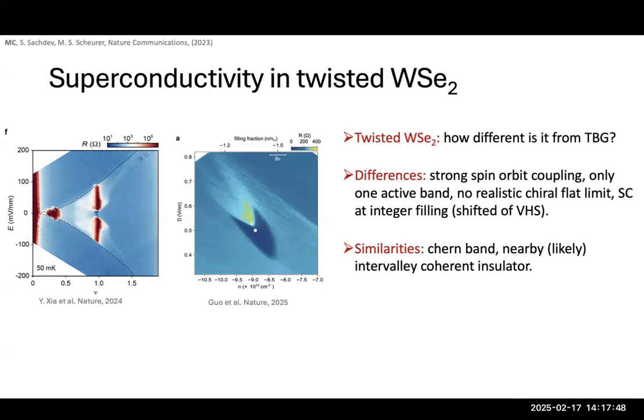And then in the Columbia experiment, they observe a peak in their longitudinal resistivity and also their Hall resistivity with magnetic field, which was interpreted as evidence for some type of Fermi surface reconstruction, possibly also compatible with this type of AFM ordering. So there's kind of good reason to think about fluctuations of an intervalley coherent order here too.